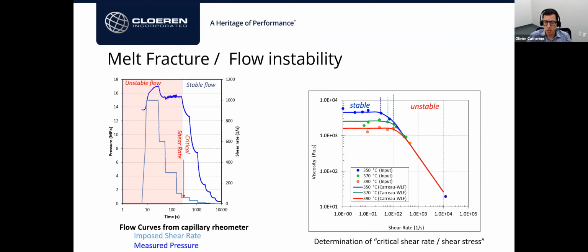Now, there are limitations as well. One of them can be that you're not able to cover a range of shear rate that makes sense for what you're looking at, right? The good thing with capillary is that it really matches what we are dealing with in extrusion or injection molding. And one quality I like with the rotational is we can cover slightly lower rates and get more precise data at low rates and a better Newtonian plateau resolution there. But then the issue is that we can't cover the higher shear rate range as well. There are different ways to deal with that, one being applying time temperature superposition and covering a whole range of frequencies by doing measurements at different temperatures.